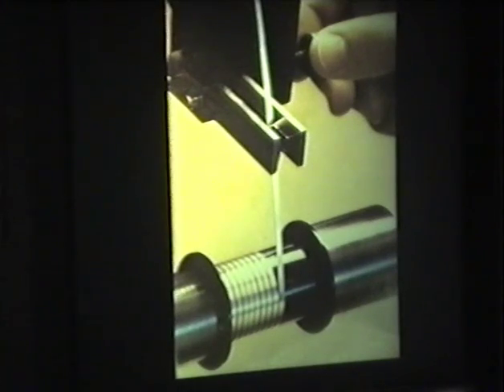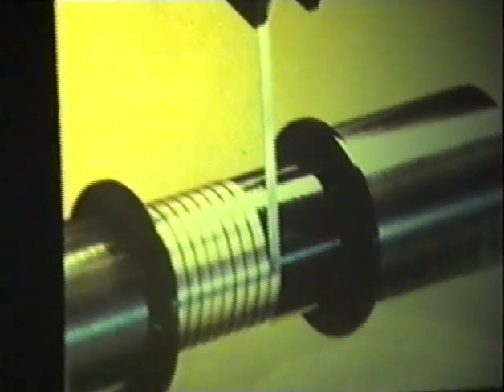And this shows one way of doing it. You can take the superconductor material, which initially looks like this, and this is bad because you've got a lot of grains where you've got to do a lot of tunnelling to get from one to another. It's much better to look like this, and put it inside a tube of silver, which you can then draw down into a tape, such as being shown here, rolled onto a spool, because you've got to remember this stuff is a ceramic. And this shows a cross-section of one of the tapes fabricated at the University of Wollongong. Here we see the black superconducting material, a ceramic, surrounded by the silver jacket after the drawing and rolling process, and then you can make magnets and other applications.